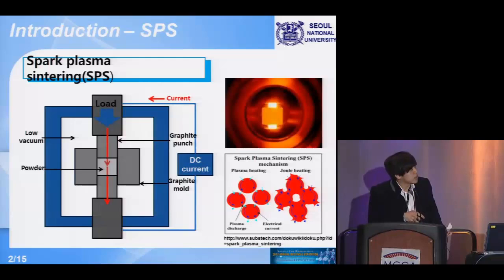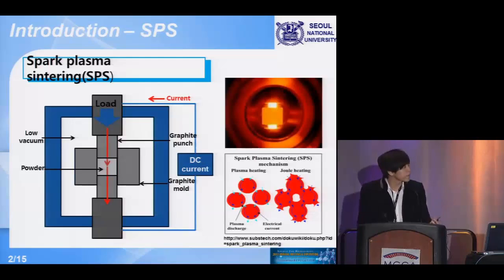I'm going to talk about spark plasma sintering first, which we call SPS. This is the brief design of the SPS. We put the powder inside the graphite mold and press it in a low vacuum state and give a pulse DC current to start the sintering. And due to the pulse DC current, the sparks and Joule heating occur between the powders.